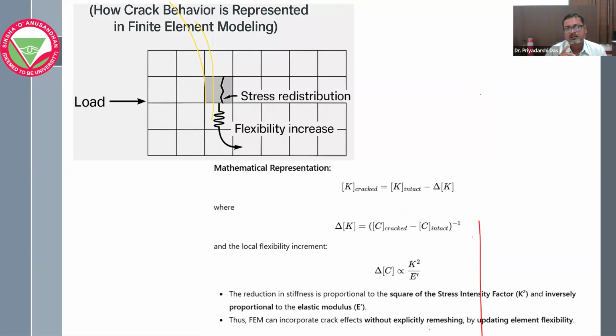If you are using the Abaqus finite element software or ANSYS finite element software, they have that library. You can form a model where assigning the cracks is quite easy. But when those models are formed through MATLAB or Fortran, you need to write the code. For that code, that mathematical presentation, you need to incorporate these formulas into the crack region. Because when a crack is formed inside the structure, it will divide the structure into two different parts. That means if L is the length of the beam and wherever the crack is formed, then that beam is discretized into two parts, L1 and L2. And at that point, you need to incorporate the crack stiffness value. From that crack stiffness, you can find the entire reduced stiffness of the structure. So this is quite essential for finite element modeling.